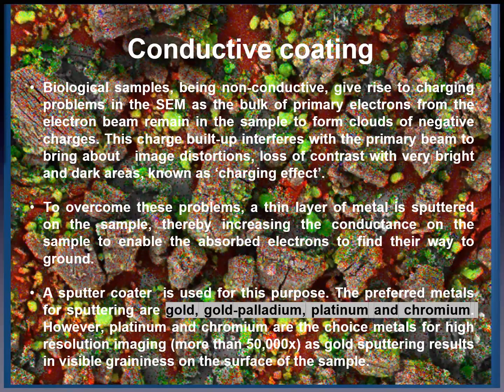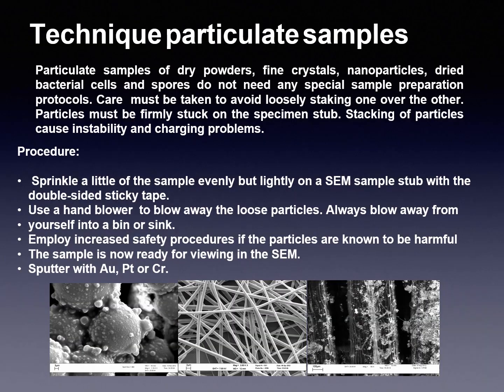The preferred metals for sputter coating are gold, gold palladium, platinum, and chromium. However, platinum and chromium are the metals of choice for high-resolution images, more than 50,000 times magnification, as gold sputter results in visible graininess on the surface of the sample.